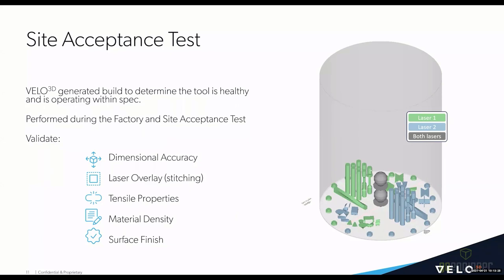Next, you have tensile properties. So you can see as printed and as machined tensile bars for each laser. Material density or lack of porosity is also verified. And then finally, surface finish is verified on several parts throughout, scattered around the build plate. This is basically the geometries that the VELO3D process engineering team has deemed as the most challenging to ensure that the tool is operating well within spec, even at some more challenging geometries.